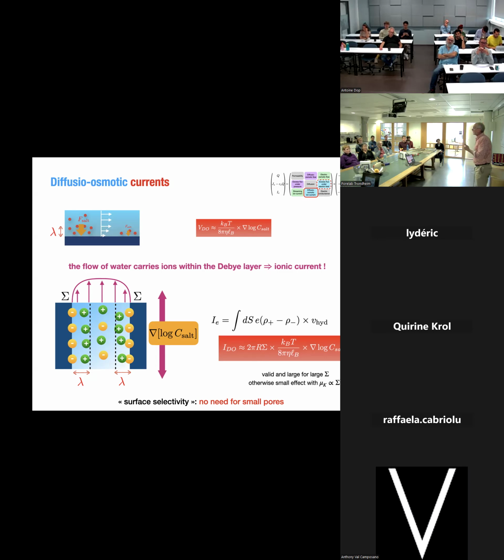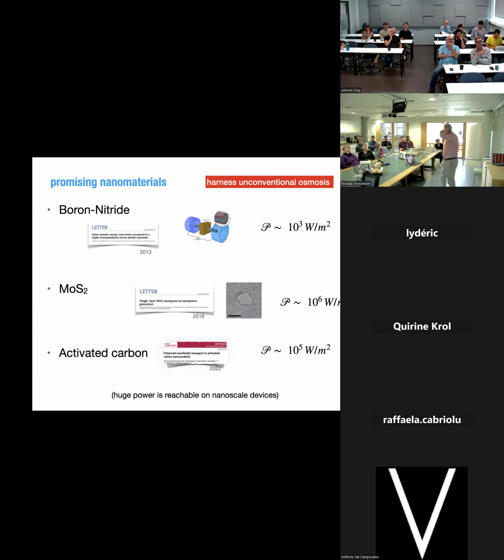So we were lucky to have a material where you have a huge surface charge, and on top of that, you have this diffusio-osmotic transport which drives the current. So you don't need very small nanopores. And about the surface charge, I think maybe Myla will tell you more later, another time, because she has been doing a lot of simulation to understand where these surface charges come from. A priori, it comes from the chemical absorption of OH minus on the boron nitride, to do a bit like a boric acid. Sorry, I'm not a chemist. Anyway, so that was luck, let's say.